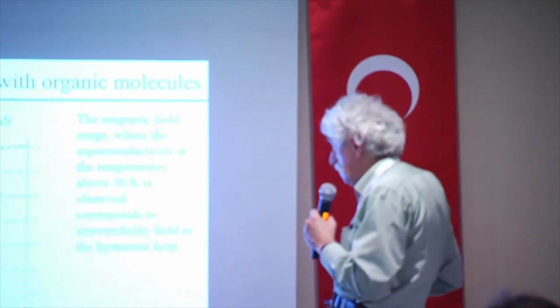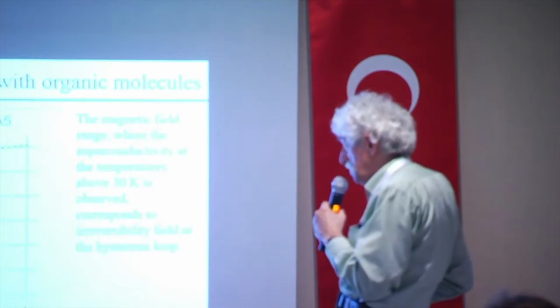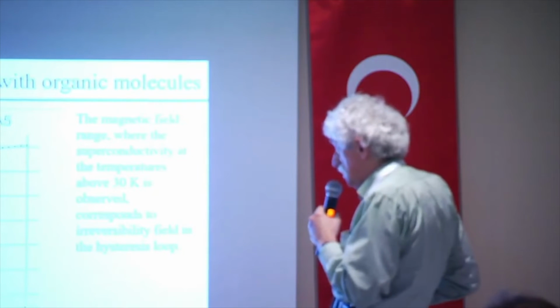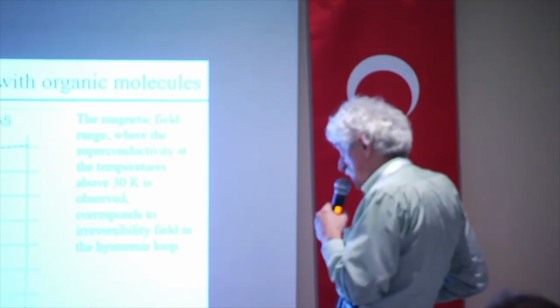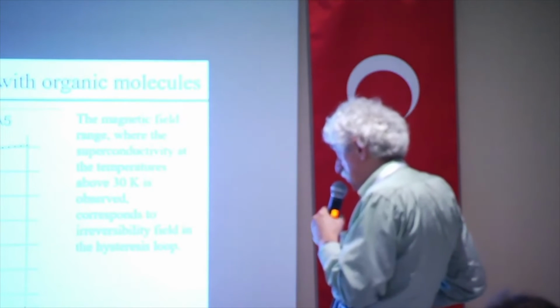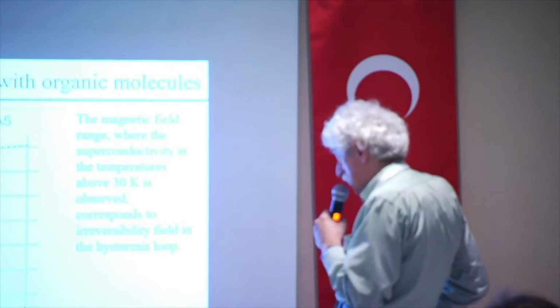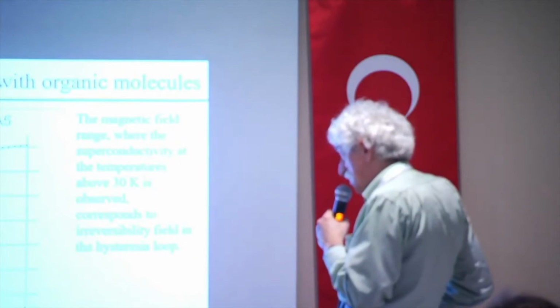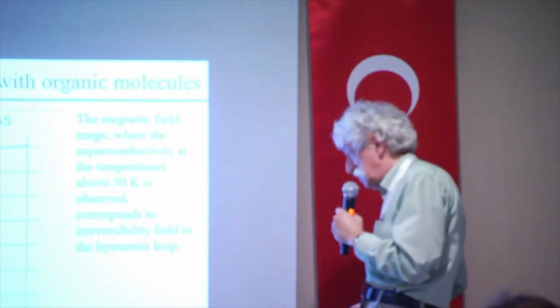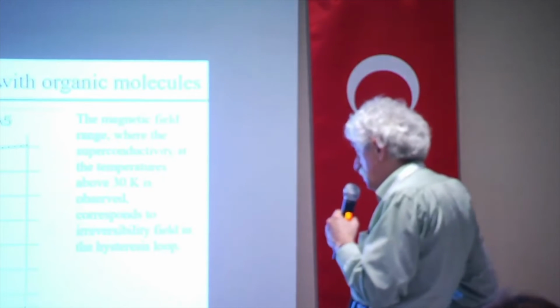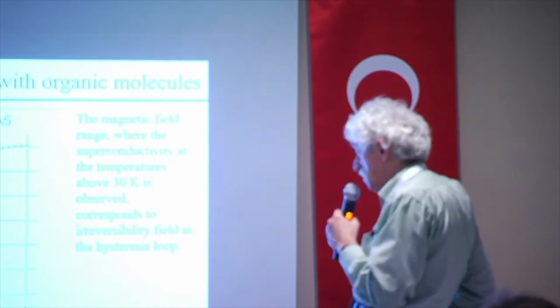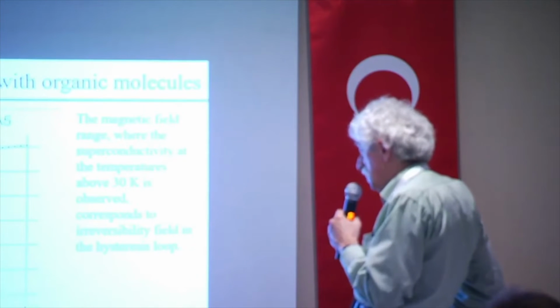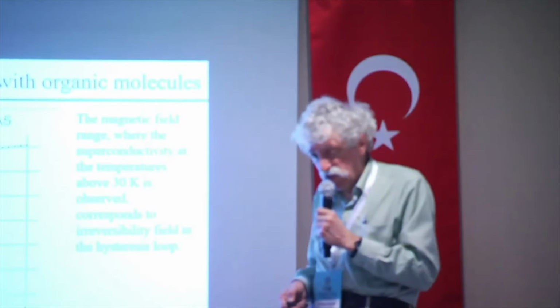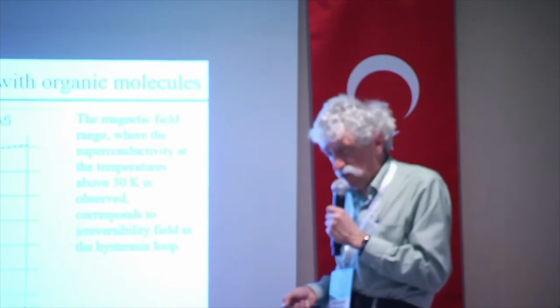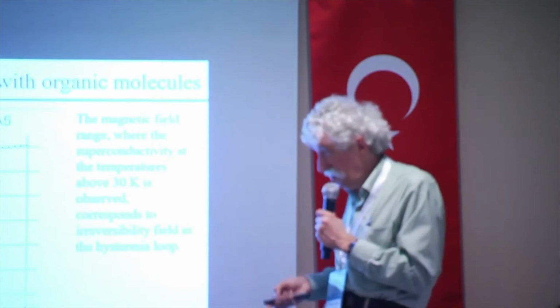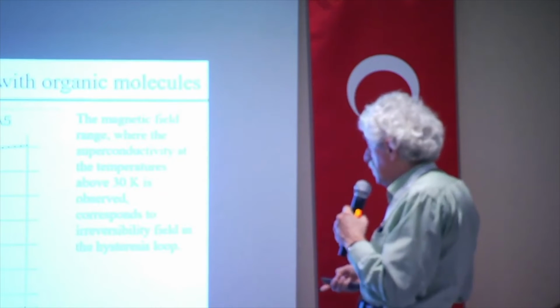And we performed several hysteresis loop measurements, and we found that in these materials there are very narrow hysteresis loops in the temperatures above 30 Kelvin. So we assume that in these materials we can increase the transition temperature quite a lot, but this is because we introduce into the material some kind of magnetic inhomogeneity, and this magnetic inhomogeneity plays the same role as structural inhomogeneity, which I will show you in rubidium intercalated materials.